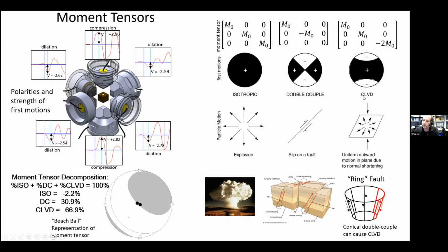And then you have this more abstract thing called a compensated linear vector dipole. So I'll refer to it as CLVD because that's a bit of a mouthful. But this is basically where you have motion in the vertical direction, compressing, and then you have radial motion outwards. But the thing is, this kind of seems like our experiments, but in this case, nothing actually opens for a pure CLVD component. It would just change shape. But the reason they do this is that if you take these three components with different percentages of them, you can make any type of fracture. So you can find out what type of fracture it was. So for here, this particular one has 2% isotropic component, 30% double couple, and 67% CLVD.